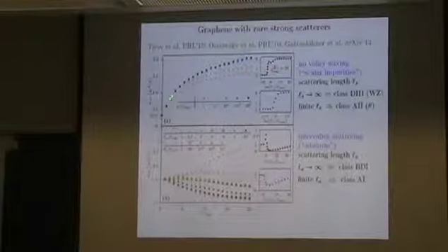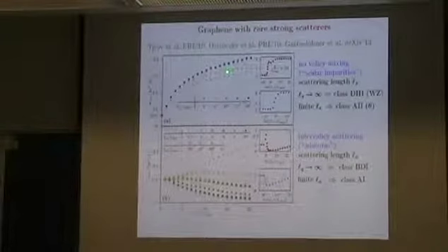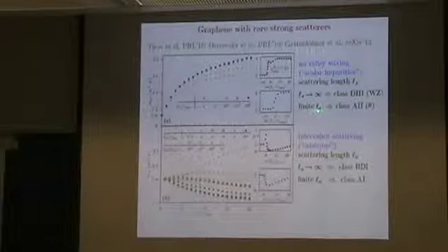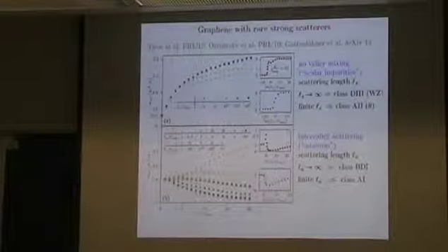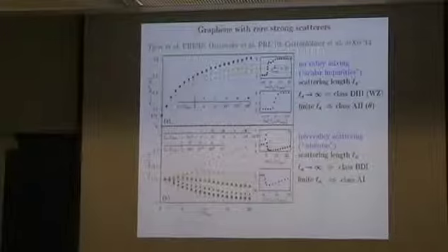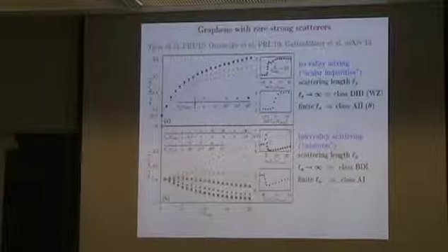Okay, so this is the conductivity as a function of length, and what you see here is that the conductivity increases when there is no valley mixing, and that's exactly what I showed you before. This is this super metal. And in fact, there are two situations here, finite scattering length and infinite scattering length. And when there is infinite scattering length, it turns out that there are more symmetries. It's just because the infinite potential preserves some particle-hole symmetry, chiral symmetry, because it doesn't matter whether it's plus infinity or minus infinity. When the scattering length is infinite, you don't know if it's plus or minus infinity.